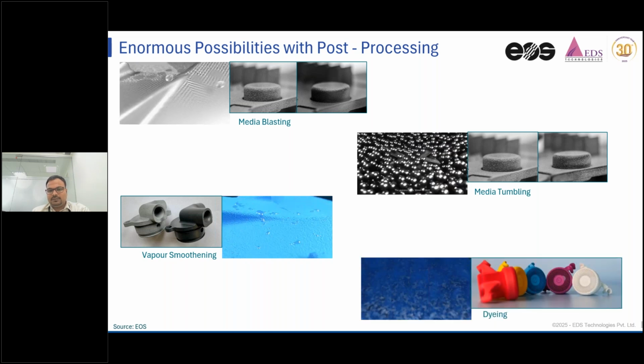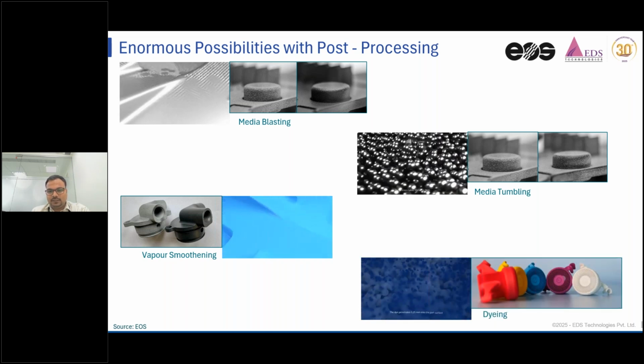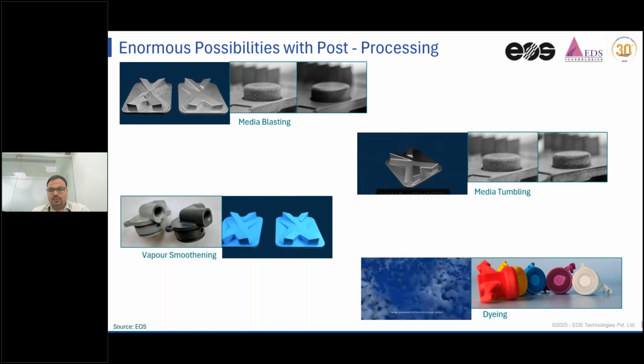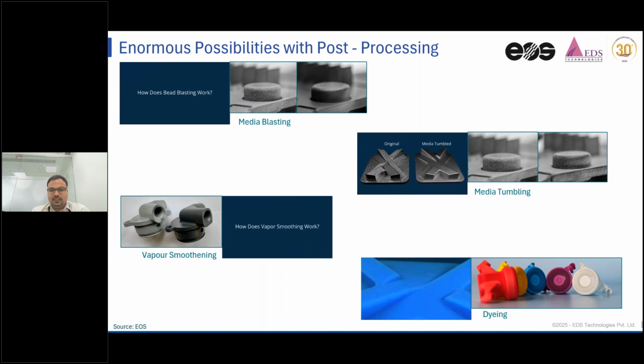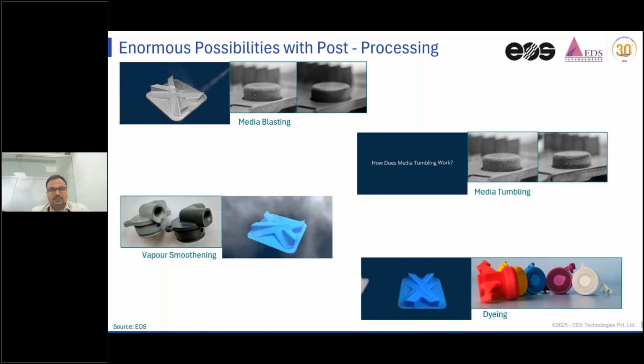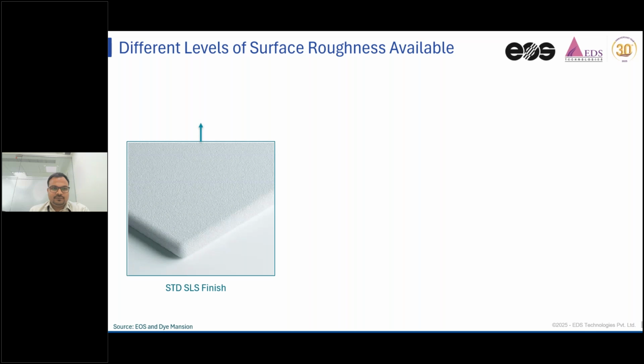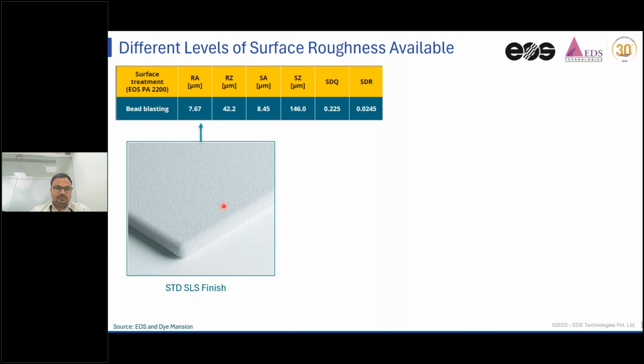And the next option is, as I said, you can dye the SLS parts in any color. Because the base color is white, you have the option to dye them in any color choice. So this is about the possibilities of different surface finishes. This is the standard finish that we get directly from SLS. This is the surface that you get. The Ra value is seen within the range of 7 micron to 8 micron, or sometimes 10 microns, depending on what orientation you put the part at. But promisingly, it will be within this range after the bead blasting.